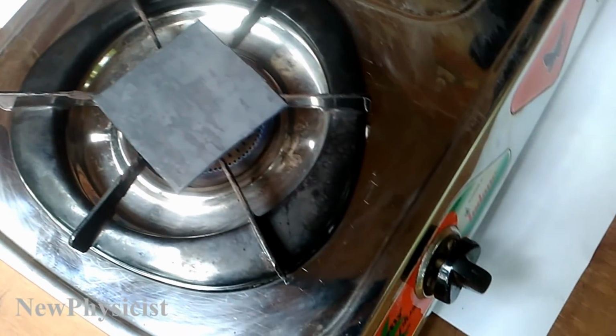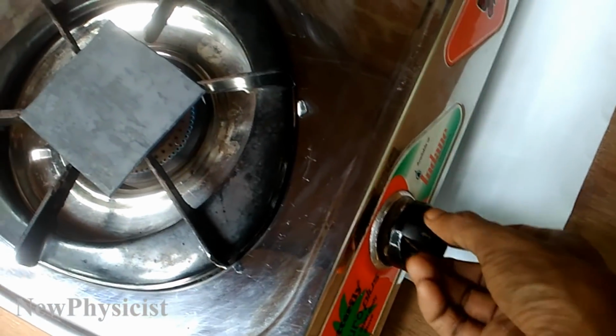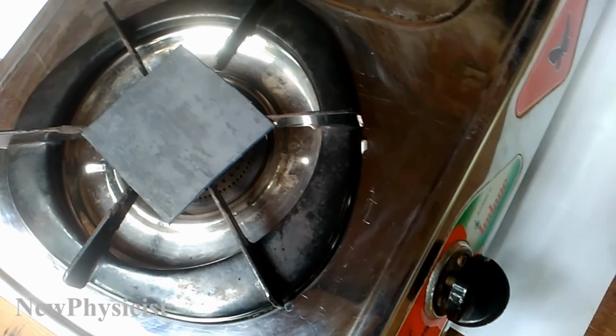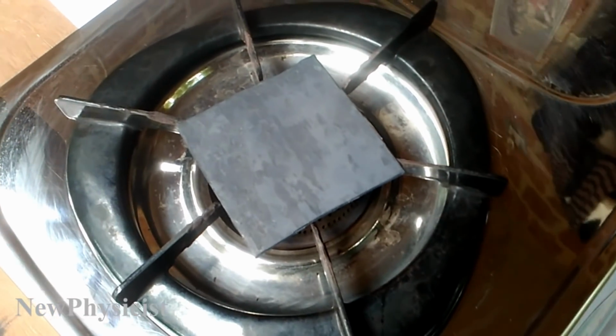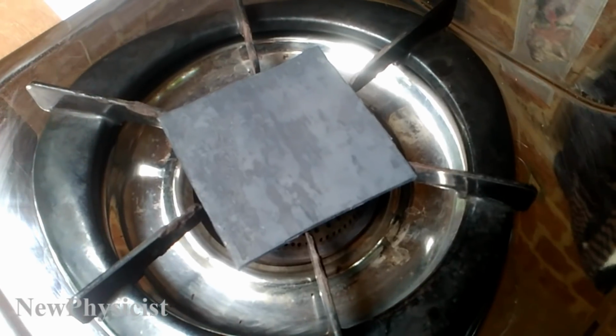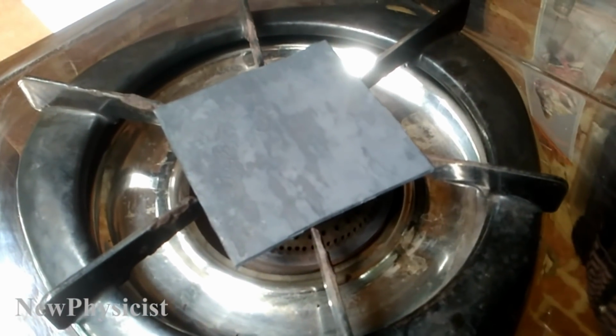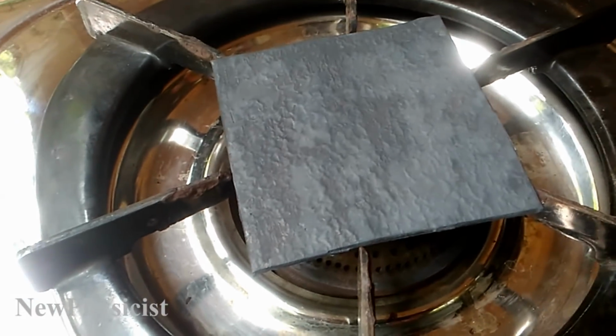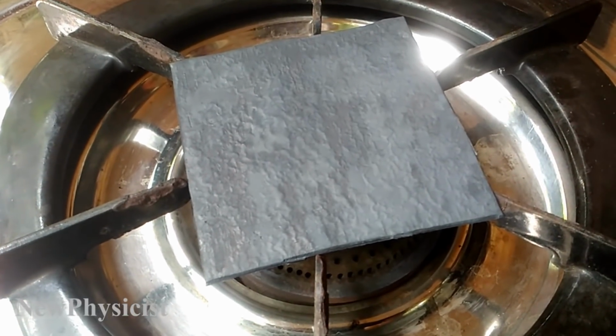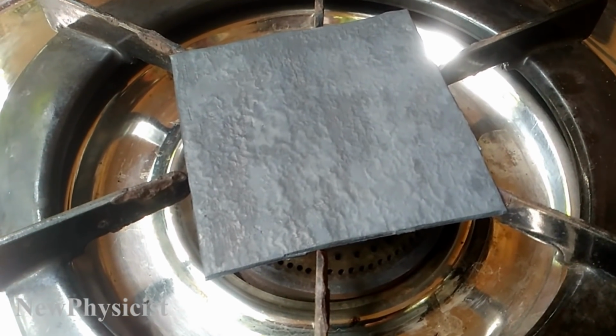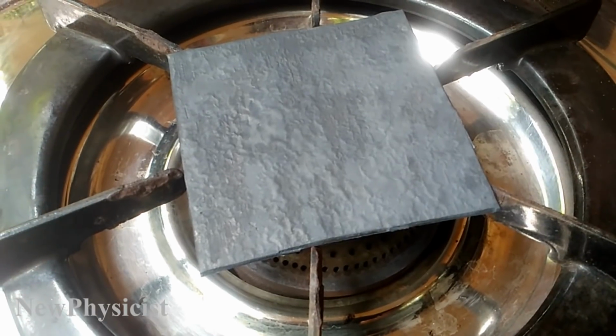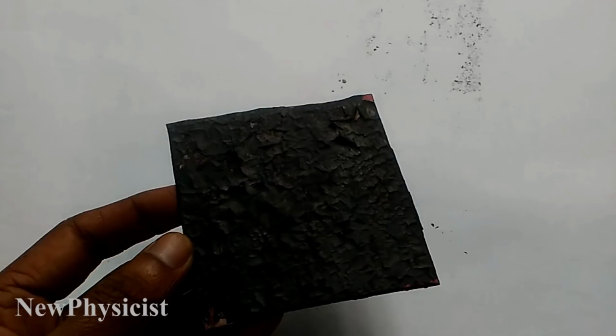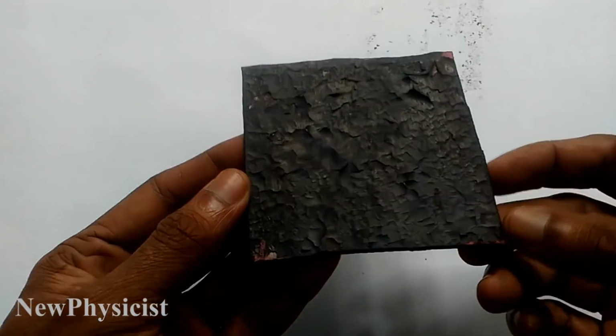When you are finished cooking the copper, turn the burner off. Don't forget that. Leave the copper on the burner to cool. This allows the copper to cool very slowly. During the cooling process, the copper and the cupric oxide layer shrink at different rates. As long as your cupric oxide layer is thick enough, this will result in the black cupric oxide breaking off and exposing the red cuprous oxide layer.